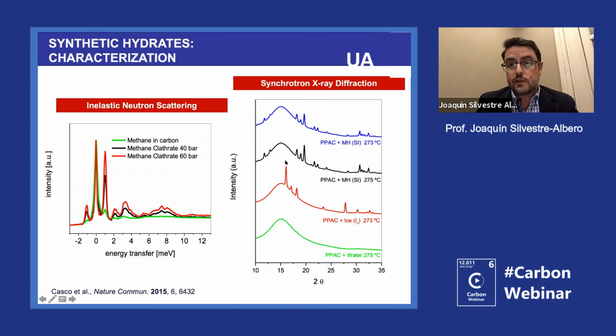And the same we observed with the synchrotron radiation. We were having at the beginning the pure carbon with water. You see the green. We were going to 0 degrees, so we were observing this ice, hexagonal ice. And then we were pressurizing the system with methane. So when we go from the red to the black, you see that you are shifting from ice to gas hydrate, to methane hydrate. And the nice thing is that you see that the ice disappears. So we have 100% conversion. And this is the most important point about the carbon. We can convert everything, as I say, in 1 hour with complete conversion.